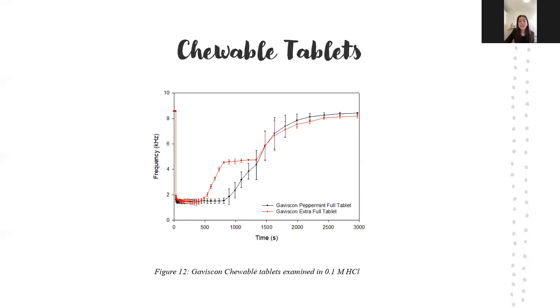So the formulation is actually a 2-component tablet. So it's bound as one, but there's a pink side and a cream side. And through observation, we actually found that the cream side breaks apart first and causes the initial equilibrium in the F-min. And then the pink side takes a little longer to dissolve and causes that second equilibrium during the deaggregation of the initial tablet dissolution. So that cream side's